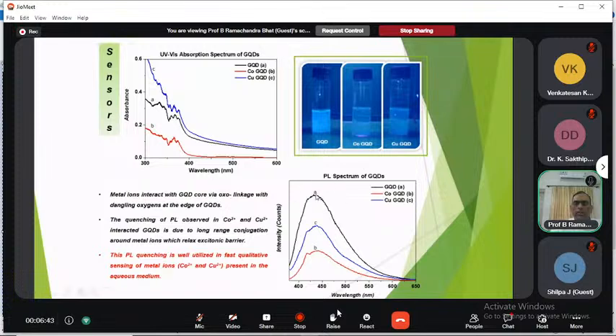around for a plain graphene quantum dots, and this intensity for the copper as well as the cobalt. So the metal ion interacts with the quantum dots through an oxo linkage with the dangling oxygen at the edge of the graphene quantum dots. Now the PL is quenching. This quenching of PL is observed with the cobalt and the copper, which interacted with the graphene quantum dots, and it is because the long range conjugation is obtained there and around the metal ions which relax the excitonic barrier. That is why the PL quenching is observed. So this PL quenching is well utilized in fast qualitative sensing of metal ions like cobalt and copper present in aqueous media.